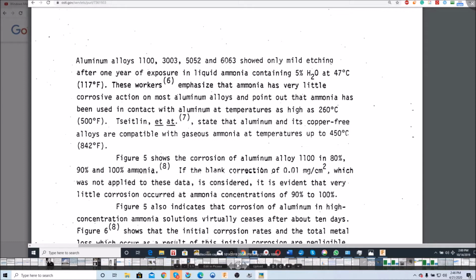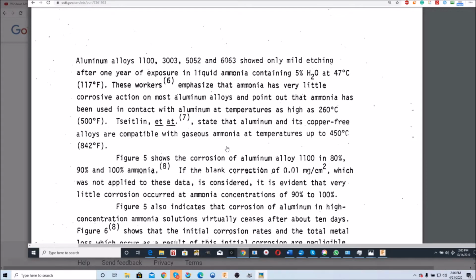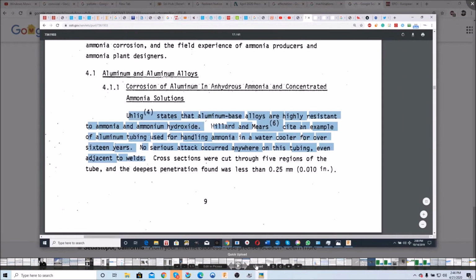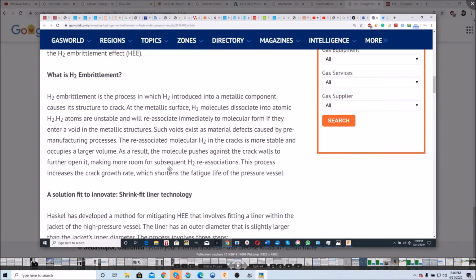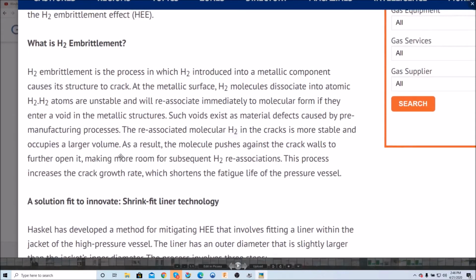But regardless, embrittlement is fundamentally the fact that the hydrogen atom is so small and it's going to permeate through just about every compound. Whereas ammonia does not appear to cause serious embrittlement. Okay, so H2 embrittlement is a process in which H2 introduced into a metallic component causes the structure to crack. So H2 molecules dissociate into atomic hydrogen, so monatomic hydrogen. Hydrogen atoms are unstable and will reassociate immediately to a molecular form if they enter a void in the metallic structure, and that's where molecular hydrogen tends to form.